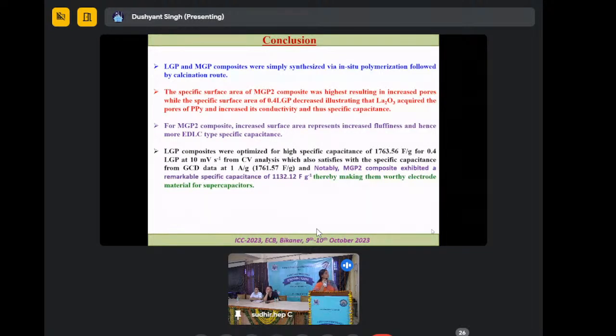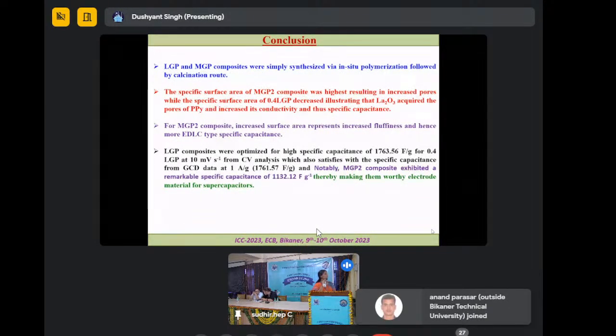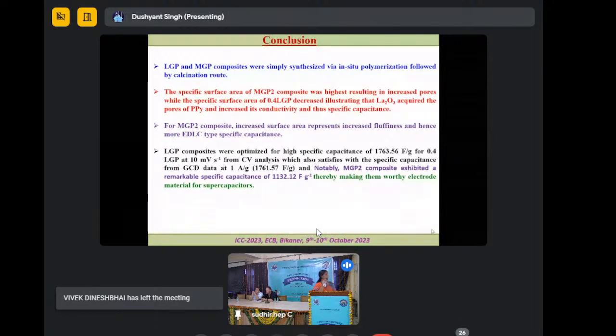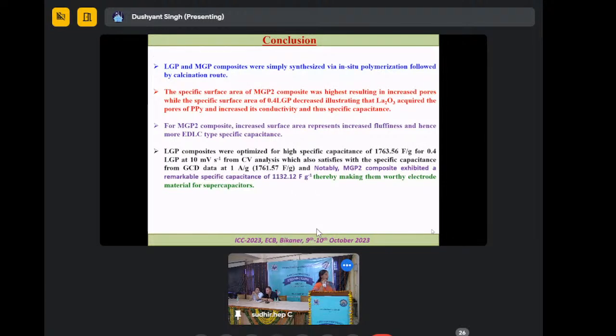This work concludes that lanthanum based graphitic carbon nitrides and magnesium oxide based composites are simply synthesized in a polymerization reaction, and specific surface area is highest, resulting in increased pore size. That concludes that these are worthy materials as electrode material for supercapacitor application. And the main thing is the higher specific capacitance of lanthanum oxide, which shows that if we dope lanthanum oxide or magnesium oxide in this graphitic carbon nitride, then these nanocomposites are suitable materials for supercapacitor electrode applications.